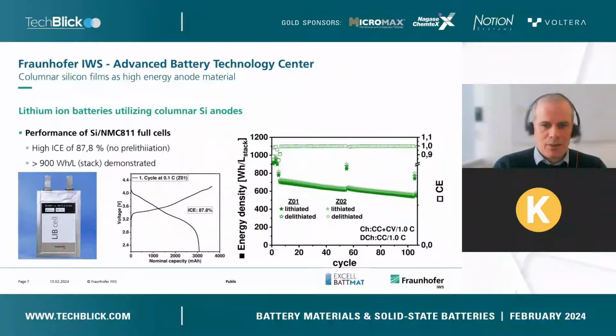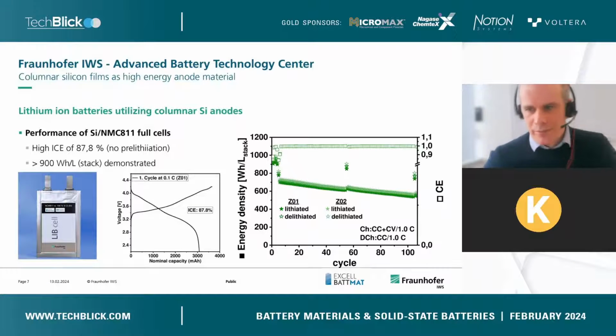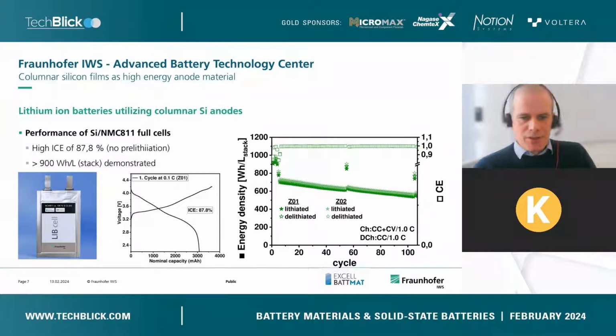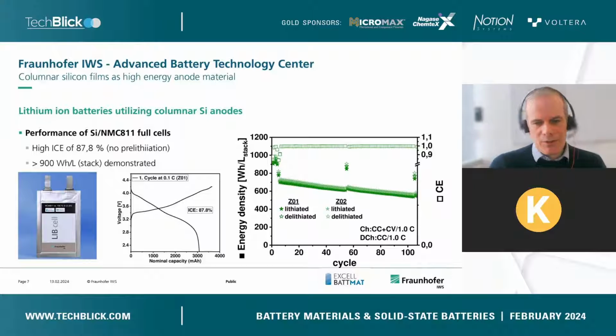So these cells obtained almost 1,000 watt-hours per liter with a high first cycle Coulombic efficiency of 87.8%, which is without any pre-lithiation. This could possibly further boost the cycle life and the first cycle efficiency, or compensate the losses which we here still have. But still, we obtain reversible cycling on a high energy cell based on our concept on cells